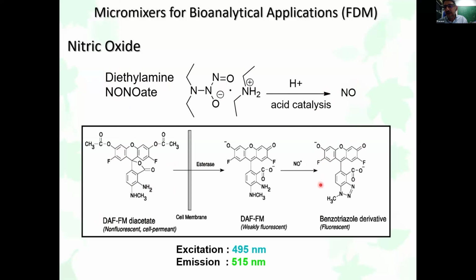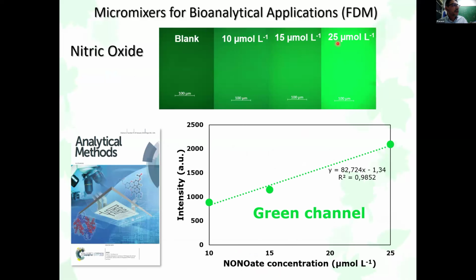So we use a fluorescence microscope to excite the probe at 495 nanometers and get the emission at 515 nanometers. So here are the results for 10, 15, 25. We don't have more points because it's really difficult to prepare these assays. And this, of course, is directly proportional to the intensity using the green channel, because the light is emitted at 515 nanometers. And here I would like to draw attention to the blank. You see here the blank is also fluorescent. So this is one issue that we have to work on in the future: to develop substrates for preparation of microdevices using 3D printing, but with smaller background fluorescence, autofluorescence. It can be really good for optical fluorescence applications.